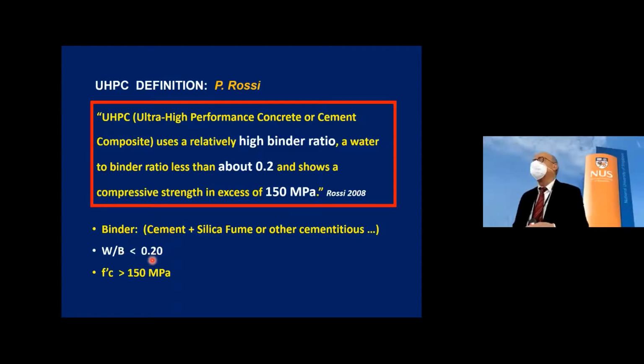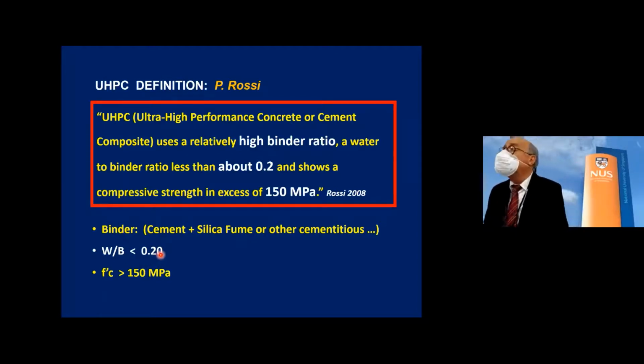If you took a course on concrete technology like I took 50 years ago, you were told, say you take 1 cement, 2 sand, 3 aggregate, 0.5 water cement ratio, because 0.5 was kind of flip a coin and you get it. You were also told that chemically, the cement needed a water cement ratio of 0.27. In other words, for all the chemical reaction to occur, you needed to put 0.27. So we never really thought of putting less than 0.27. And then the last item, the compressive strength more than 150 megapascal.